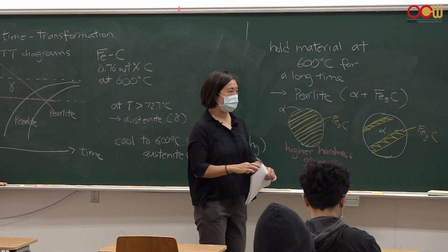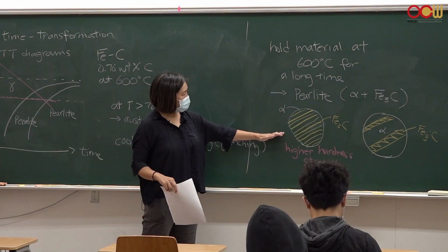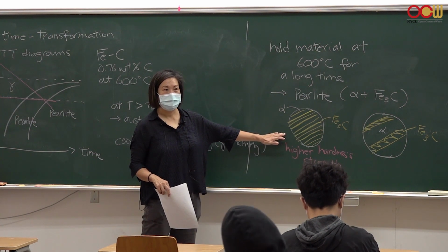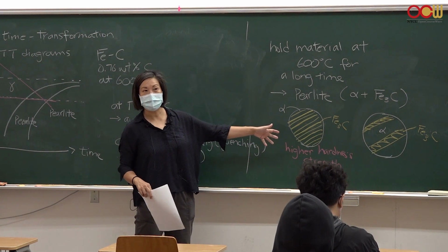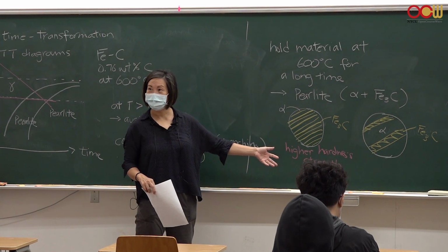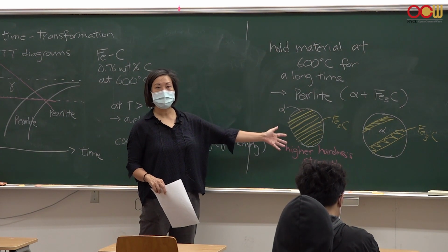This will be more ductile, right? Easier to bend, this one. The reason why this has higher hardness and higher strength is that more grain boundaries inhibit slip or dislocation movement, right? Dislocations can't move through as easily, so it's harder and also higher strength.